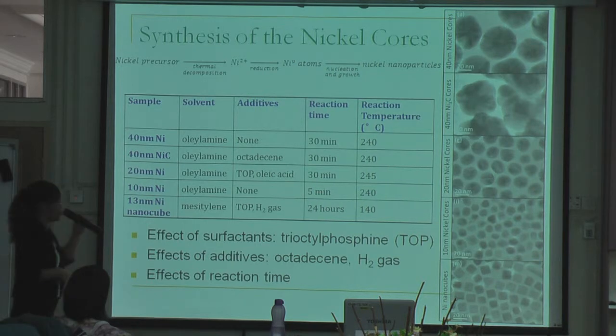To prepare nickel nanoparticles of smaller size, there are a couple of strategies that we can apply. One of them, to prepare the 20 nanometer nickel, is to use a surface capping agent, in this case trioctylphosphine. Trioctylphosphine can bind strongly to the surface of nickel, which helps to slow down the rate of growth of the nickel nanoparticles. That's why it's possible to get particles of smaller size by using a strong surface binding agent. Another strategy to obtain smaller particle size is by reducing the reaction time.